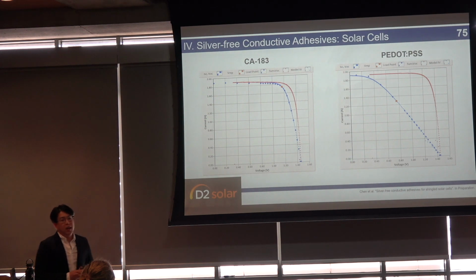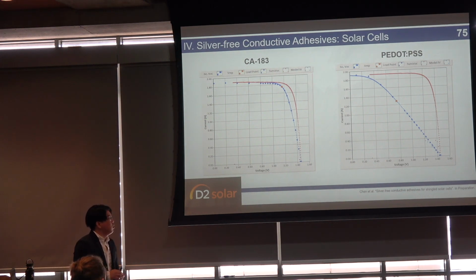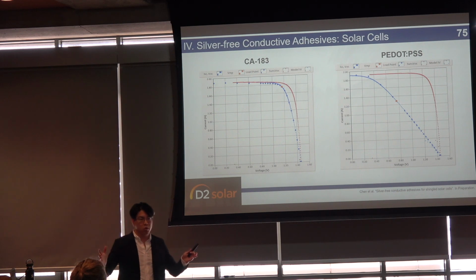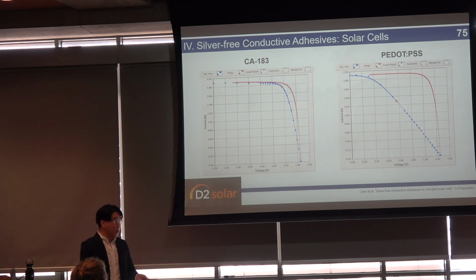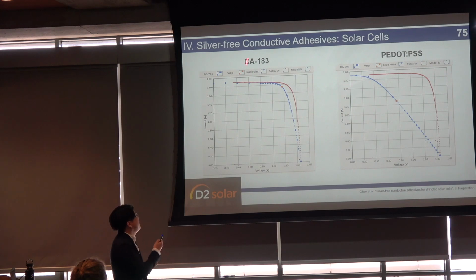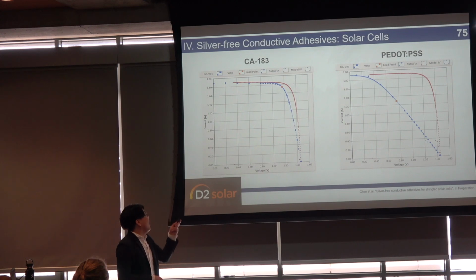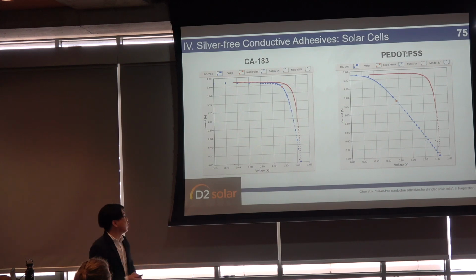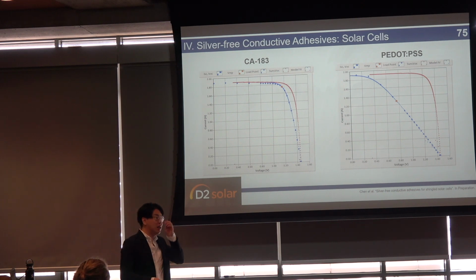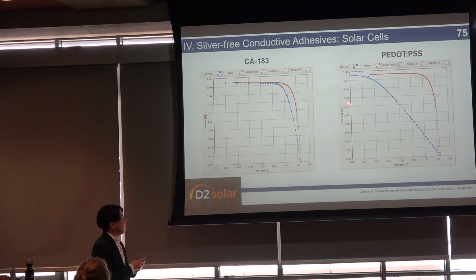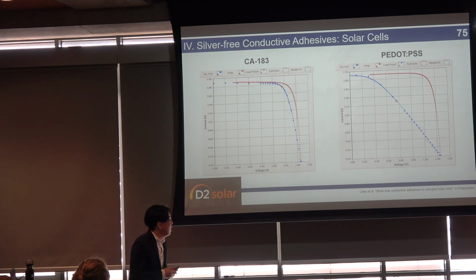So we worked with a commercial group to shingle solar cells, and what they did was they took these commercial solar cells and they laser cut them, and they glued them together, in comparison to CA183, which is just a commercial standard. It's a standard 70 to 80% silver in epoxy material. We see that for PEDOT:PSS by itself, because it has a very low conductivity, it has a very poor bulk resistivity, the series resistance is extremely high, and the cell is very bad, right? You can remember that we care about how square this blue line is. Well, this is not very square. It doesn't look very good.